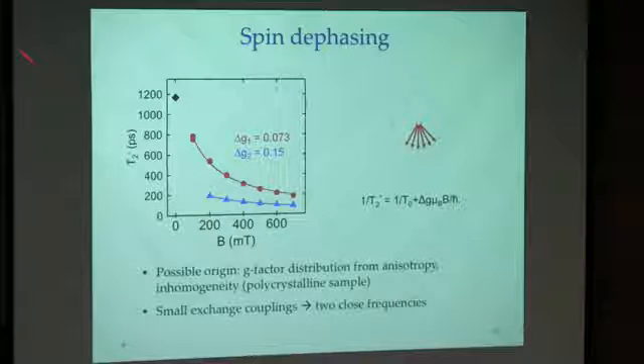OK, so what you measure is actually a coherent dephasing. Yes, it's dominated by the spin dephasing. This is not the true spin decoherence time. So that's why we call that T2 star. It's an ensemble measurement. But the delta G is really a measure of how much the NMR frequency changes from spin to spin.